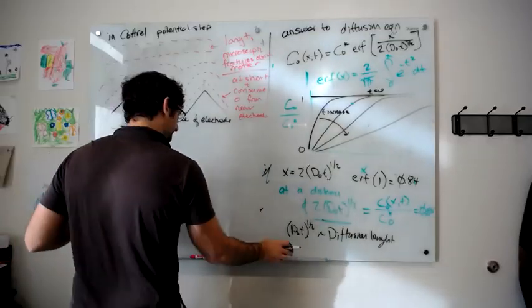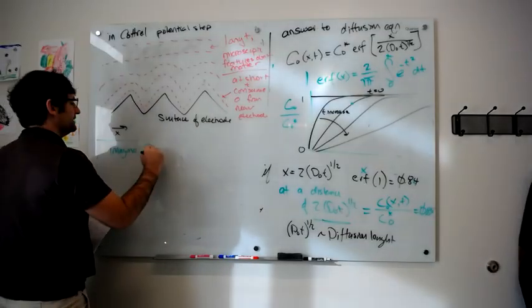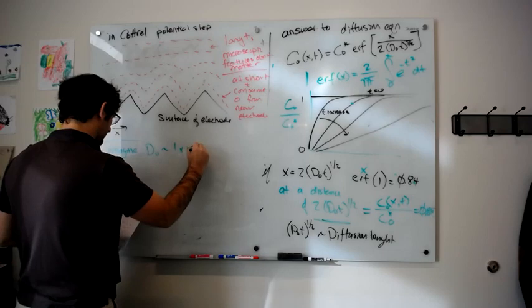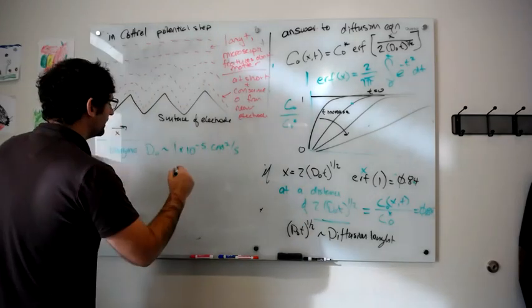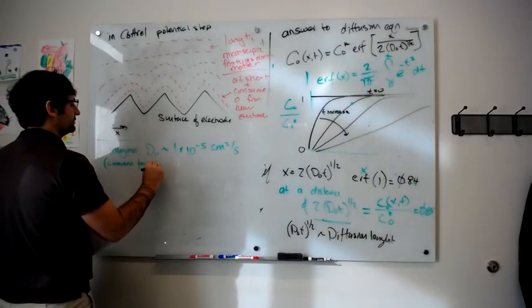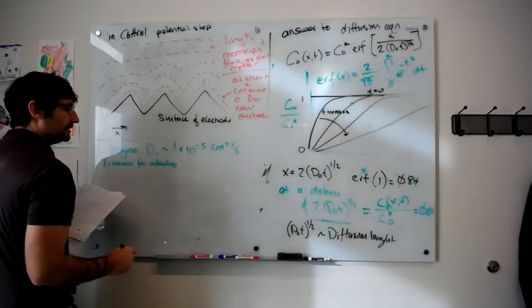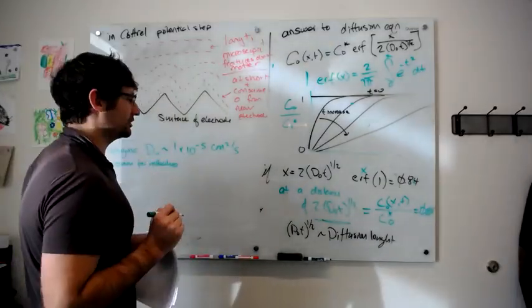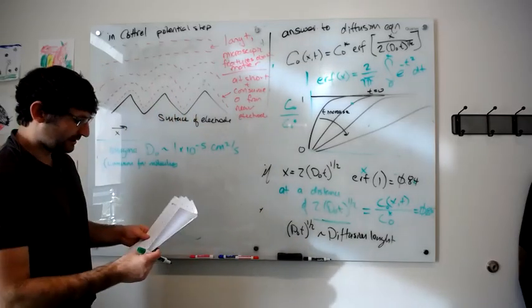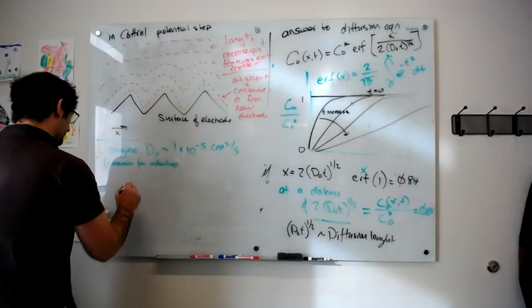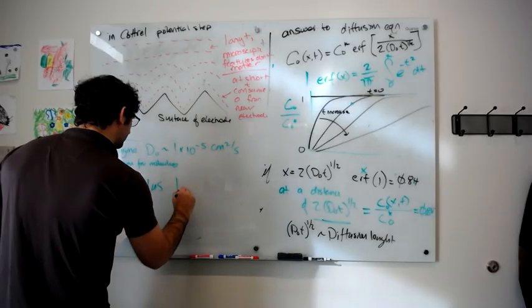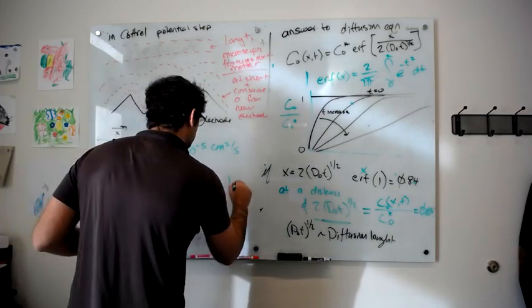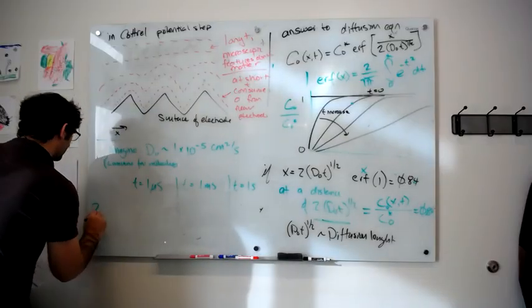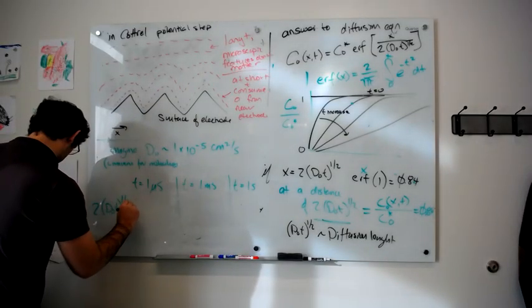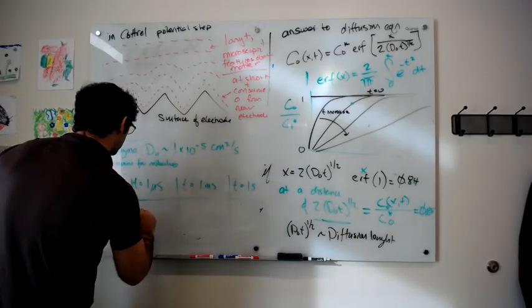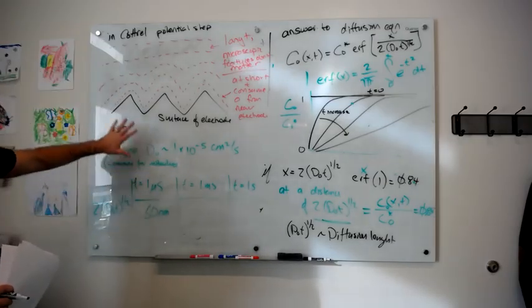So let's do an example here. Let's imagine D_O is 1 times 10 to the negative 5 centimeters squared per second. And this is common for species in solution, for molecules. Okay, so we can use this diffusion coefficient to calculate, based on this diffusion length, about how much of the electrolyte will be depleted. So if t equals 1 microsecond, t equals 1 millisecond, or t equals 1 second, we can calculate 2 (D_O t)^(1/2). And we find that it's about 60 nanometers. Okay, so in 1 microsecond, you've depleted 60 nanometers away from your surface.